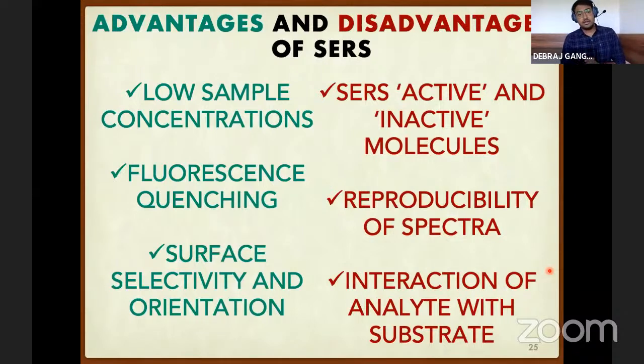So what are the advantages and disadvantages of SERS? In SERS, the first advantage is that we can record for very low sample concentrations. Even picomolar or femtomolar concentrations can be recorded using SERS. Another advantage is fluorescence quenching. If the sample is fluorescent, it will not affect the SERS spectrum. We may get a very strong SERS signal from such samples. The third advantage is surface selectivity and orientation. We can select a surface, and then we can control the enhancement. There are some particular groups like the thiol group, which can adsorb easily on the metal surface and thus produce a stronger SERS signal. And the disadvantages of SERS are that there are some SERS active and inactive molecules.